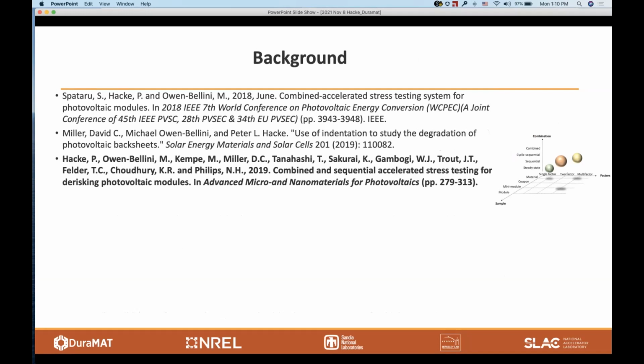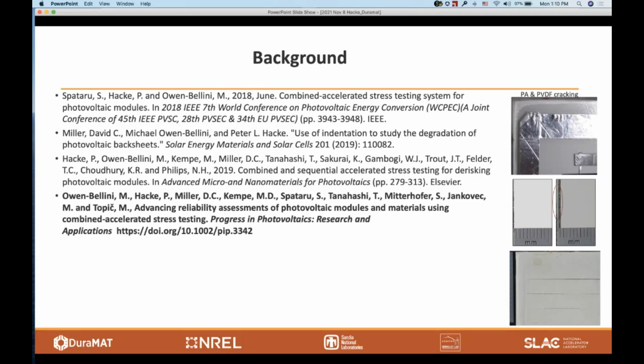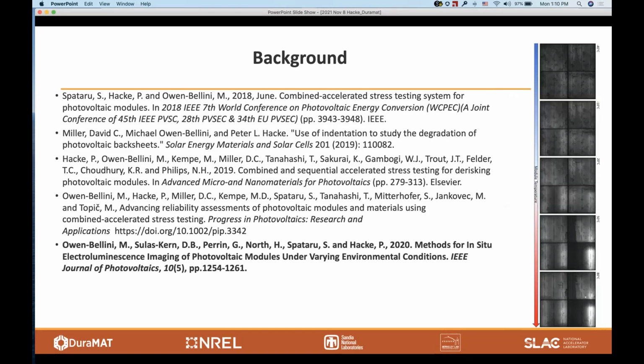We've shown here how different stress factors combine, and in the combined accelerated stress testing, we're seeking to represent the factors of the natural environment, and the combination that they see in the natural environment. And that's discussed here. We've also published how combined accelerated stress testing finds the degradation of polyamide and PVDF cracking that's seen in the field, pretty much out of the box. We've shown how in situ electroluminescence can show how cracks or disconnects may exist as a function of temperature from minus 40 to 80 degrees C. And this has been reproduced in a number of publications in and out of DuraMAT.